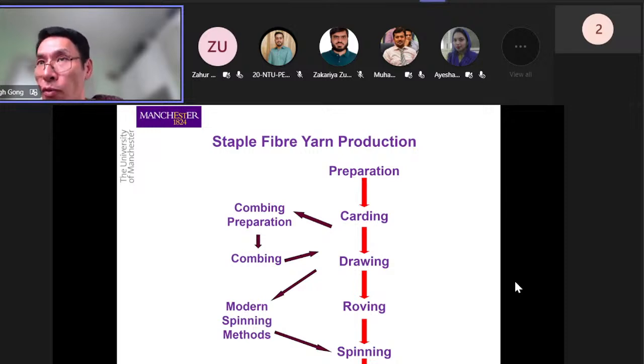So you have to open the fibers, and typically it goes through a carding process, which is essential to individualize the fibers. And if necessary, you may have to go through combing to further straighten and align the fibers, and then do drawing. And then you produce the yarns, whether you go through roving or not, or you can go through other modern spinning systems to make the yarns. So there's a lot of mechanical process going on.